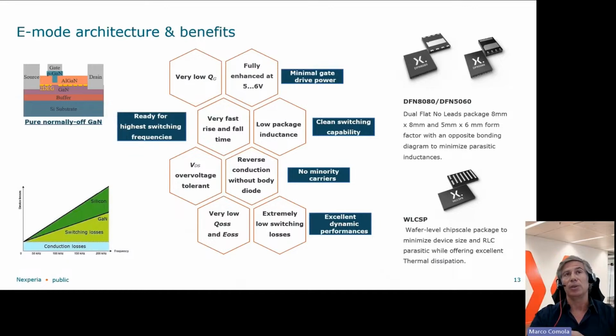And again, as I told you, you have a very low gate charge and a very fast rise and fall time, so it's ready for high switching frequency. And just a comparison that you can find on the left side and then the bottom side. If you compare the gallium nitride versus the silicon at the same on-state resistance, device losses versus frequency, of course, the conduction losses depend just on the on-state resistance, so they will be the same. In terms of switching losses, of course, the gallium nitride shows the benefit, a better performance.